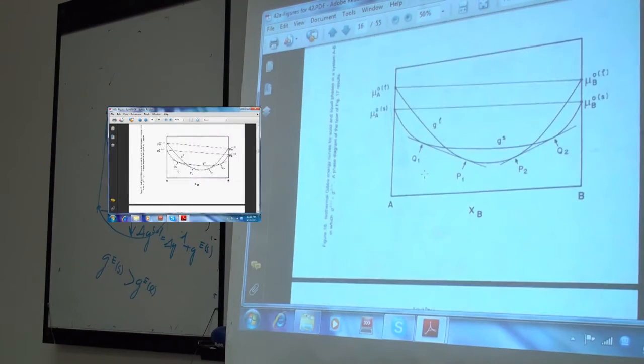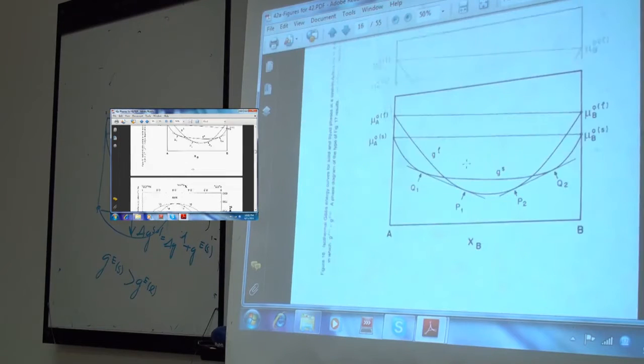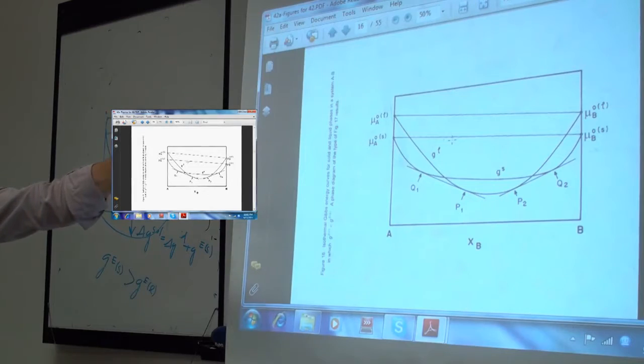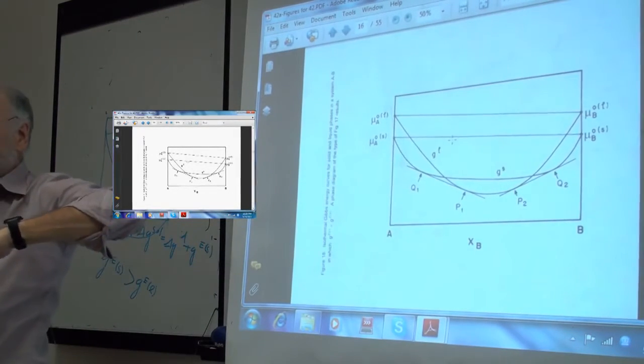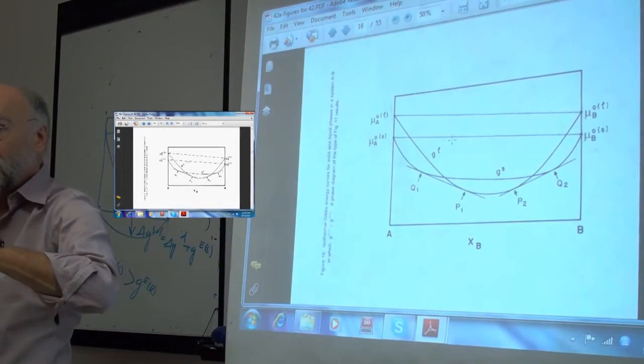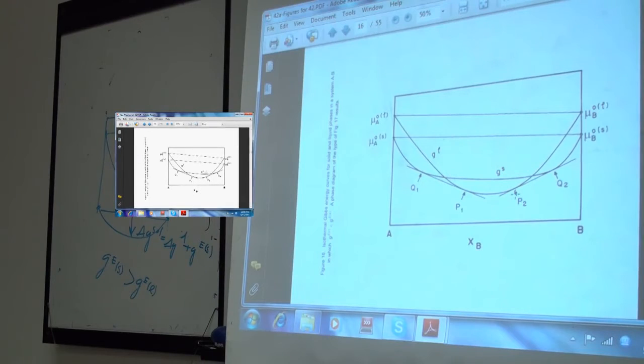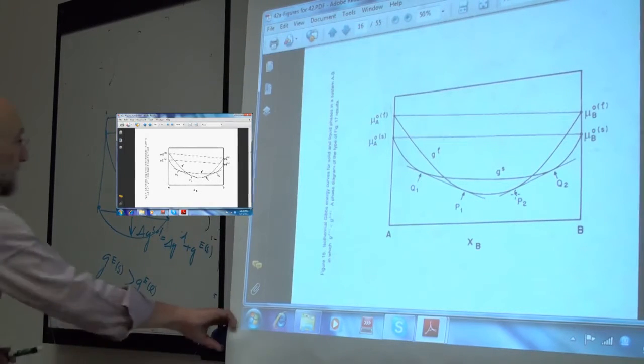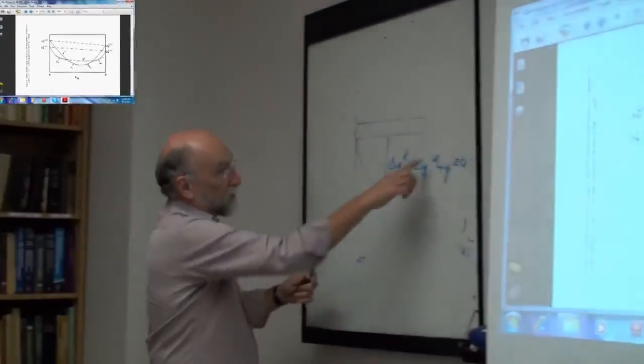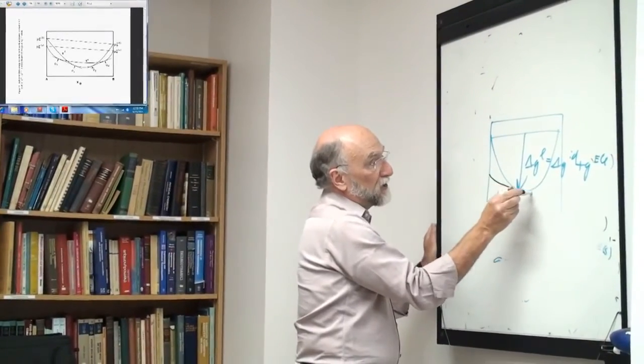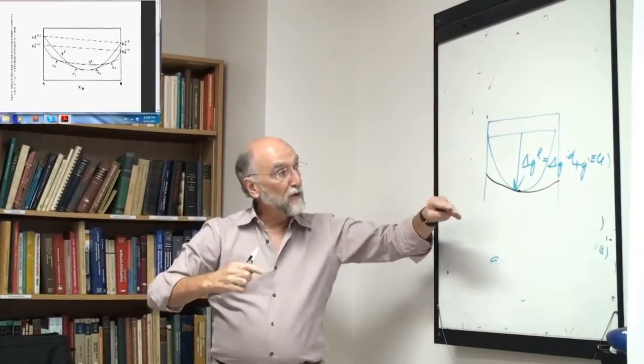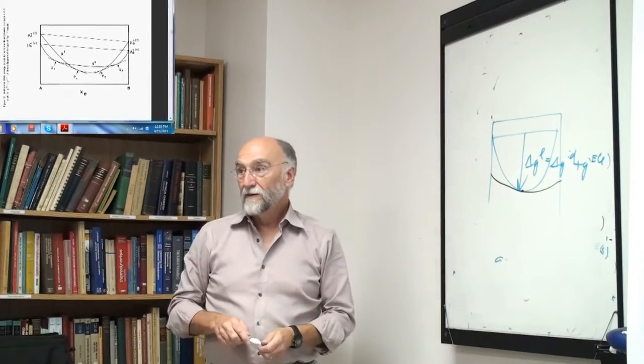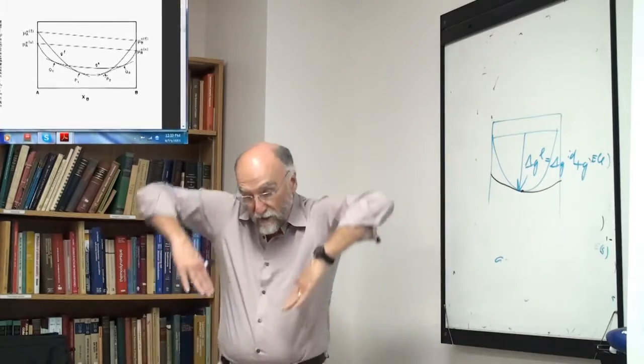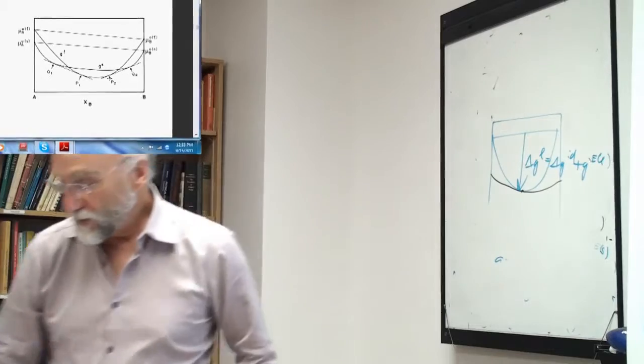Now, as you lower the temperature, say we start, so that was 700 degrees. That was this temperature here. So now as we lower the temperature, the solid phase continues to descend. And now your two common tangent lines, which are like this, move along like this until P1 and P2 touch. When this goes down to a low enough temperature that P1 and P2 touch, then your liquid curve is like this, and your solid curve now touches at just one last point. That's the minimum point. You go to lower temperatures, the solid phase comes right off. So your common tangents move like this and then disappear. So when P1 and P2 become coincident, that's the lowest temperature.